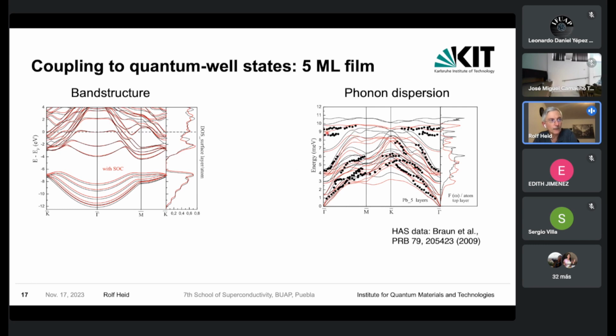And in particular, if you look at the upper part, you see here two branches which reasonably nicely correlate with the prediction from theory. But the agreement is definitely better if you include a spin-orbit interaction.